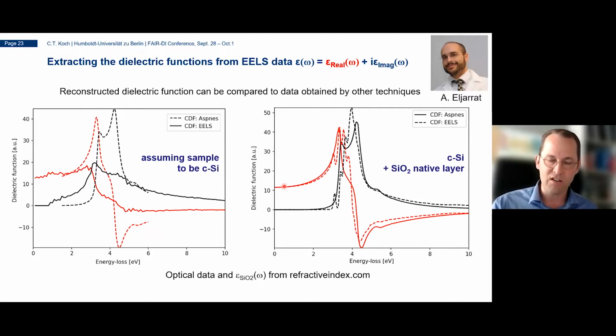But when Alberto now assumes that there is also native oxide on the silicon, which makes sense if you know how the silicon sample was stored, right? It was not processed under protective atmosphere, but was exposed to air, and then the native oxide can grow. If you have that information, you can make that assumption and build that into the model. And now reconstructing the dielectric function of this material looks much better. The solid line is the optical reference data, and the dashed line is the reconstructed dielectric function, and you can see much better agreement.